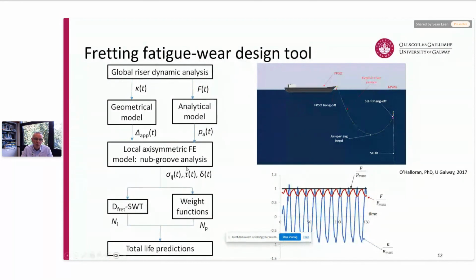And then the local axisymmetric nub groove model allows us to quantify the stress tensor as a function of time and the surface shear and relative slip parameters, which we need for Defret, for example, or indeed for the explicit wear simulations as a function of time. And then we can come up with total life predictions if we include our crack propagation.